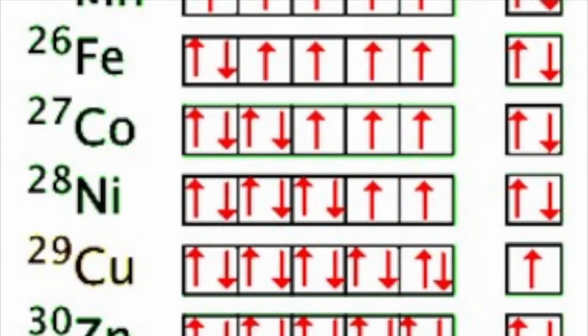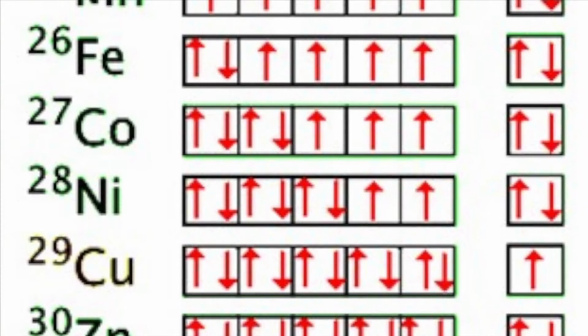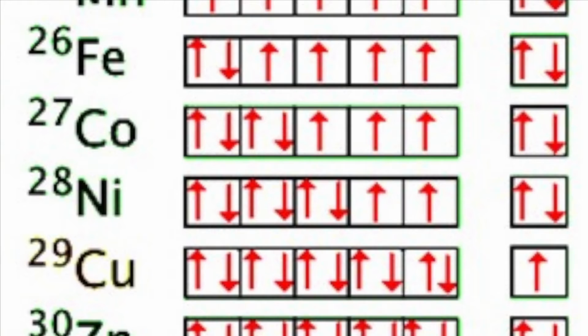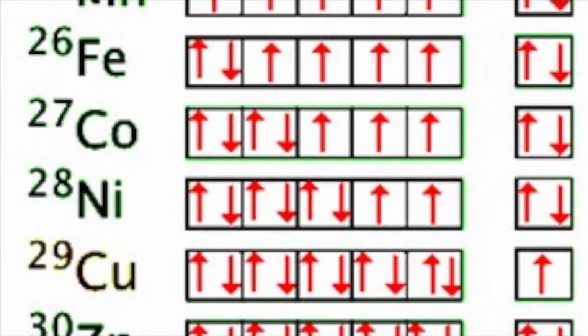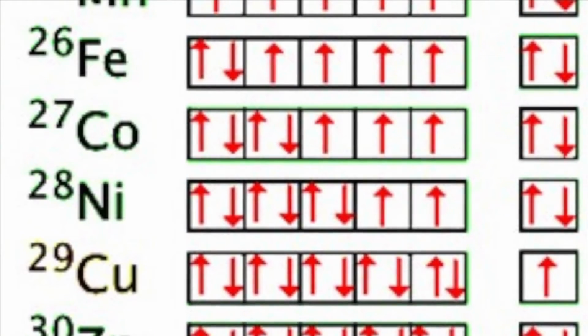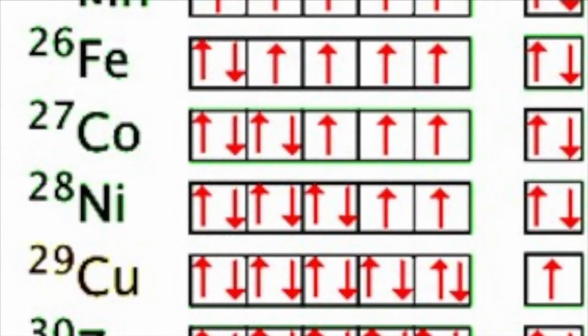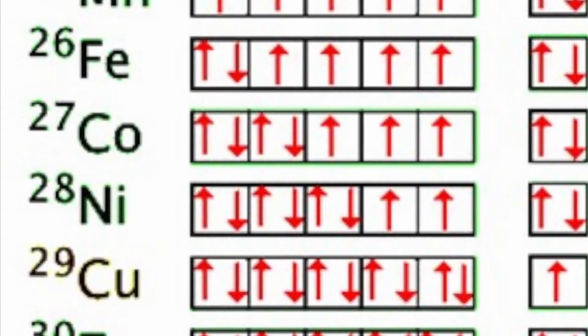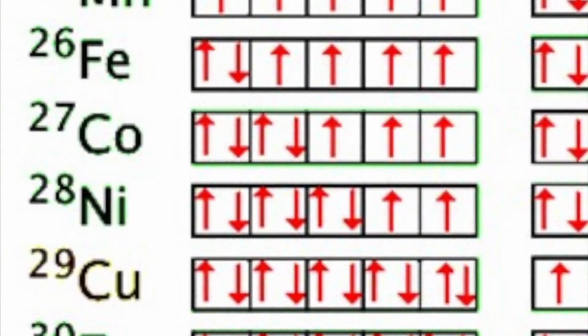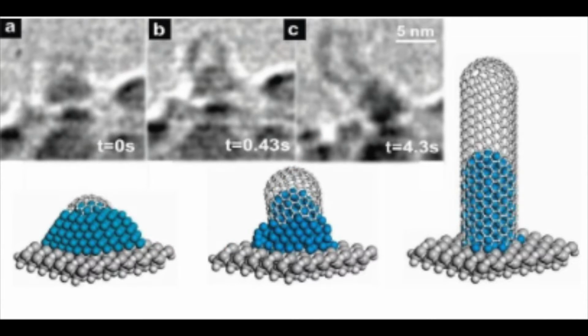It's been observed that there is a correlation between the growth and nucleation of CNTs and the electron structure of the metal used as a catalyst. The metals most currently used for CNT synthesis are nickel, cobalt, and iron. These metals have few d orbital vacancies. The carbon is initially deposited and thus activates the catalyst, forming metal carbides on its surface. A carbide is a compound composed of carbon and a less electronegative element. The metal carbides segregate part of the dissolved carbon, causing them to form the first graphene layers.